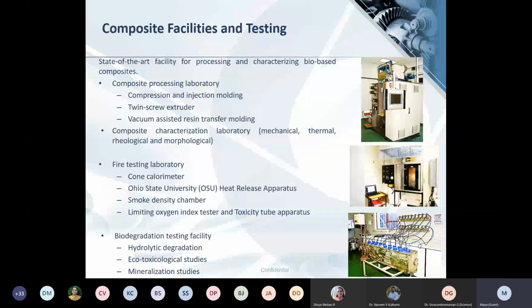So as per ASTM standards, for the material to be claimed as biodegradable, it's not enough that it should just disintegrate or fragment. It is necessary that 90% of the carbon in the material should be converted to carbon dioxide. So mineralization tests measure that. It measures the amount of carbon dioxide that is emitted from the material during biodegradation.